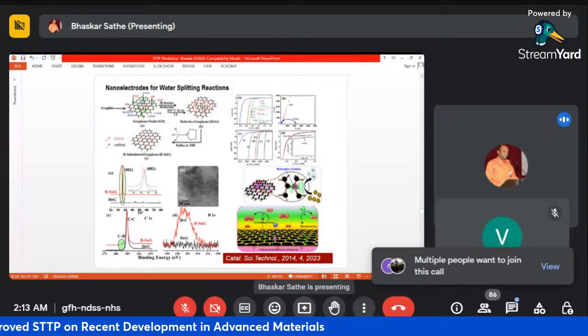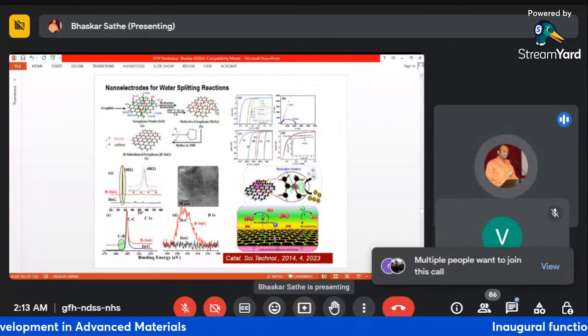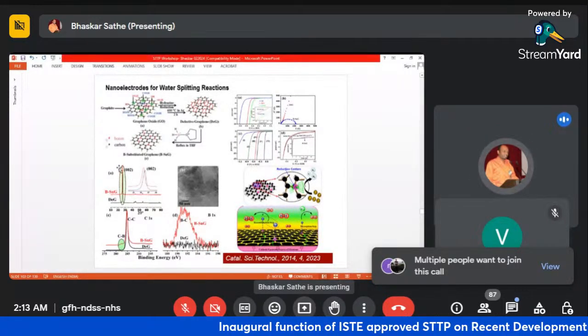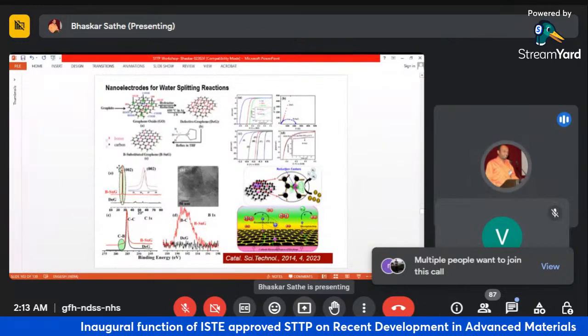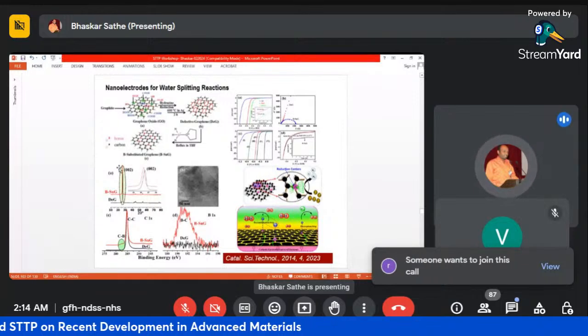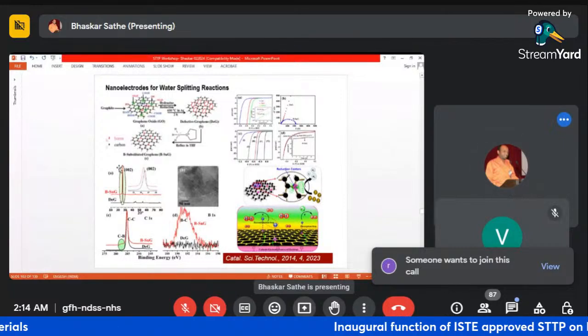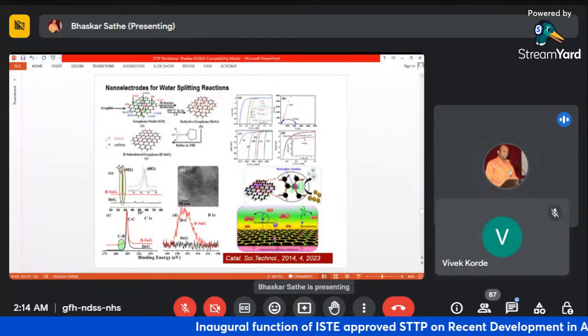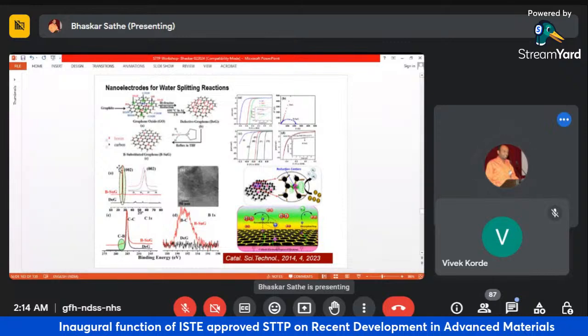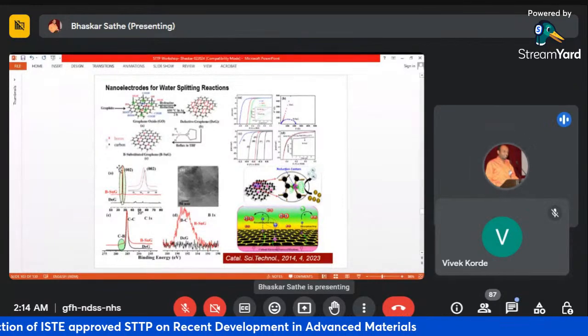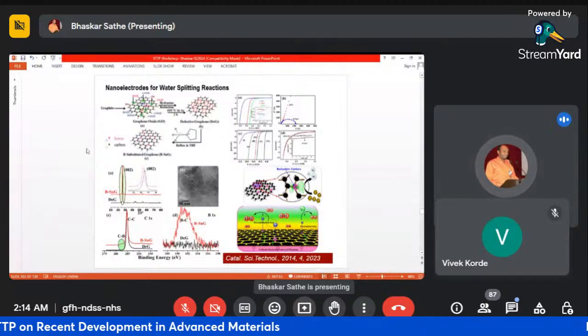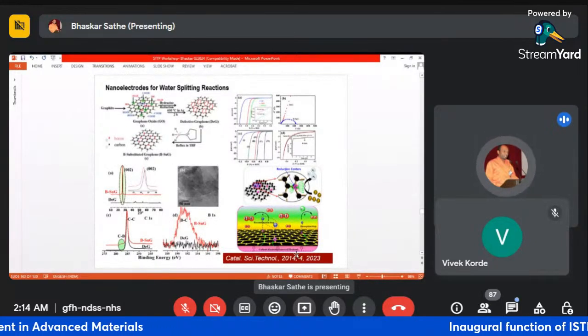We have developed graphene. Graphene is further modified by developing pockets through defects, and the defects are filled by boron, that is systematic substitutional doping of boron in the network of the graphene. That is the boron substituted graphene we have seen, and that center becomes more active as the electron source to produce hydrogen from the water molecule. Right? So this is the case. Actually, I don't want to go into more detail. If you need details, you can go to this article.